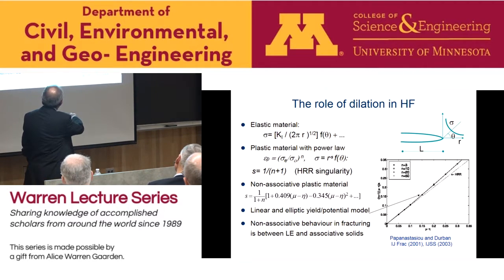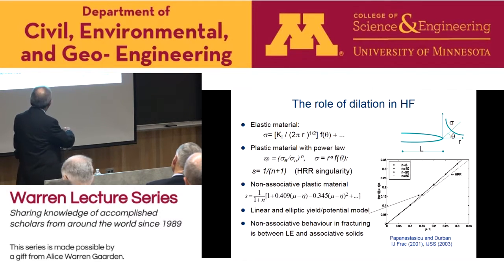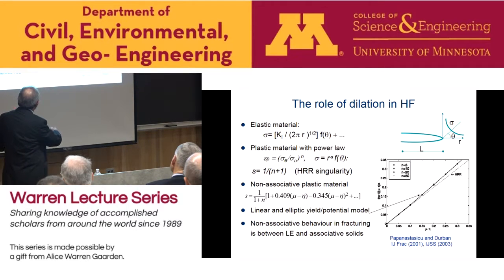For elastic material, we have the square root singularity, 1/2, okay? Now, if we go to plastic materials and we can express the effective plastic strain as a function of effective stress in this power law form, then we will have a singularity of this form, R to the minus S, and we have this well-known singularity in the fracture mechanics community. HRR is called Hutchinson, Rice, and Rosengren, which is S equals 1 divided by N plus 1, which is basically weaker than the elastic singularity, okay? It's weaker than the elastic singularity.